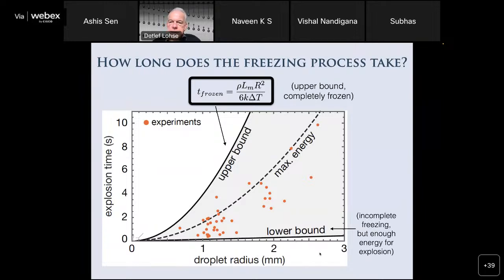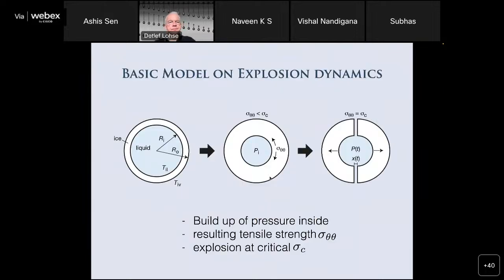And in fact, we have some other bounds here. We have a lower bound here. This is incomplete freezing, but enough energy for this explosion. You can also calculate this. This is here. And you can also calculate the maximum elastic energy, which is then available for transfer to kinetic energy. And this is along this curve. And you see that all the data are nicely in between these bounds.